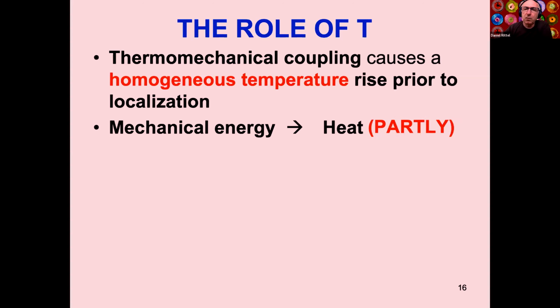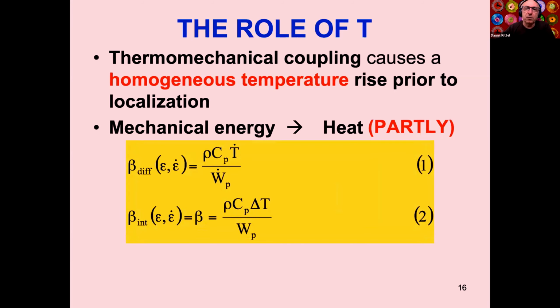That's long known. Well, one should say here that it's partly transferred into heat, not totally transferred into heat. And here we can define the well-known Taylor-Quinney coefficient, this one, the integral, which is the ratio of the thermal work to plastic work. With the years, it has become evident that, contrary to what Taylor and Quinney measured or hinted, this is not a constant. And the early work of Ravichandran at Caltech and co-workers has shown that, in fact, it's a function of the strain and the strain rate.